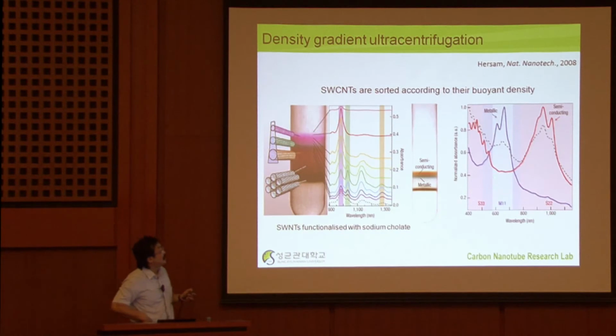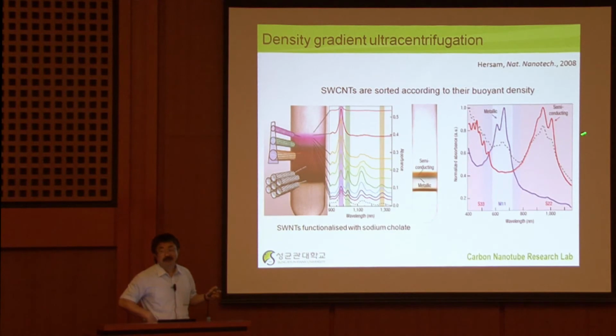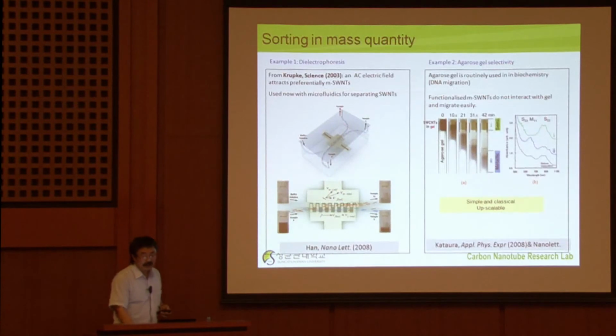For instance, if you look at this absorption spectroscopy, this is a semiconducting peak. This is a metallic peak. See, this guy does not have this metallic peak, but only the semiconducting peak, whereas this guy has no semiconducting component, but only the metallic component. So you can actually separate them, okay? And the separation yield nowadays is quite high, more than 95%, which is excellent. And some people try to have mass production using this approach, using microfluidic channels. And then also this Japanese group, they use this agarose gel to produce a large amount of separated nanotubes.